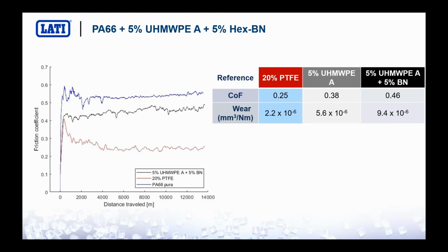But not all the synergists work, because, for example, we repeated the same experiment of the slide before, but changing the carbon nanotubes with boron nitride. And in this case, the boron nitride seems to damage the tribological improvement provided by the polyethylene. So a higher friction coefficient, but also a higher wear factor. So this was a bad result.